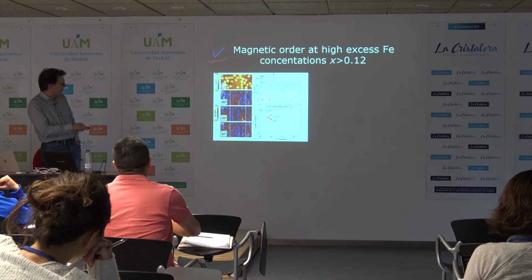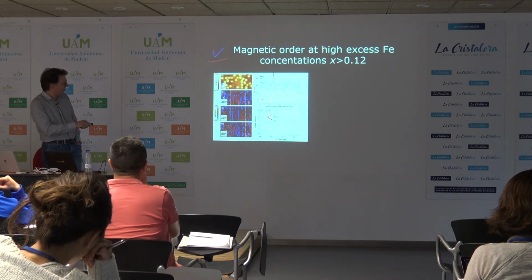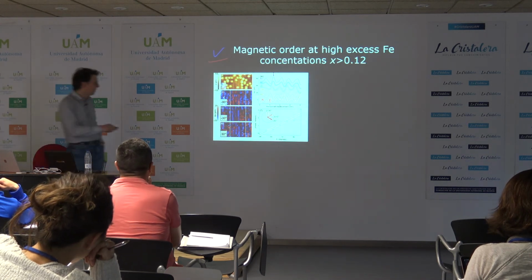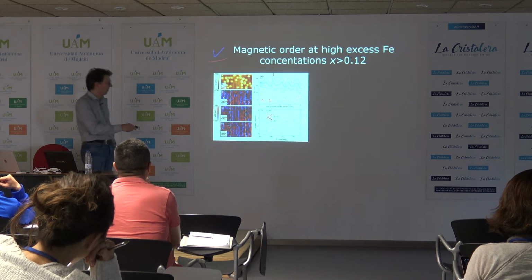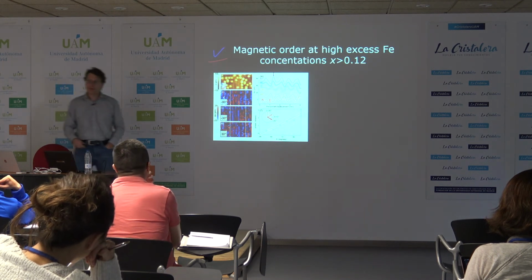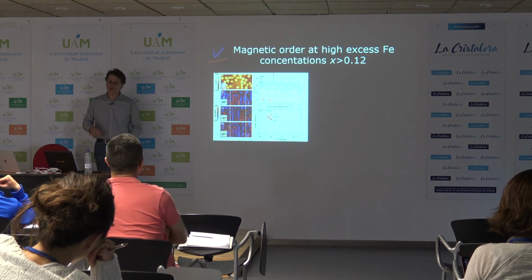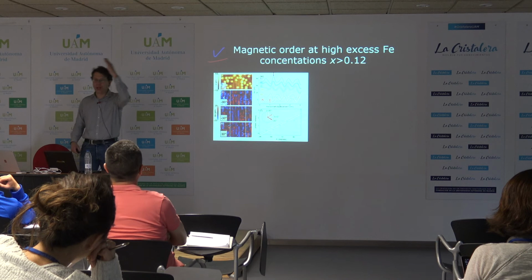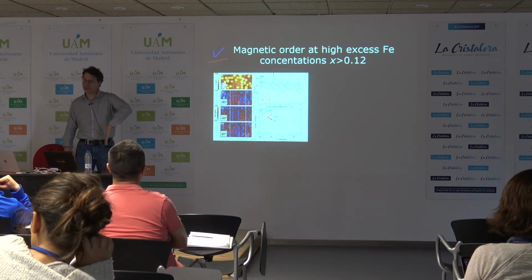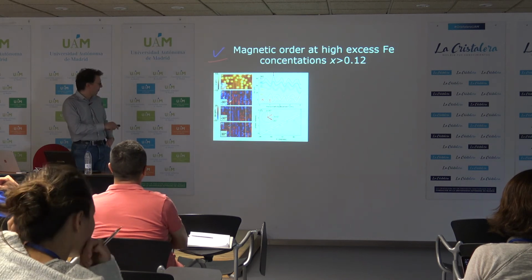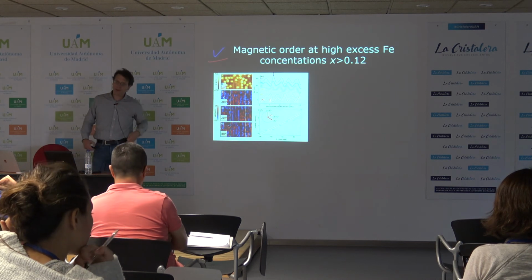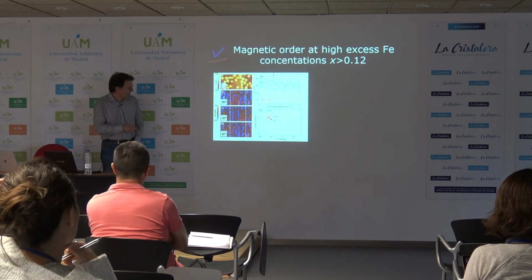It's maybe not so easy to see in these images, but here's a series of line cuts taken in the same location, and you can see that these maxima move as a function of field angle. So we can clearly show that the magnetic order shown here is in fact a spin spiral, and as we project on different spin polarizations of the tip, the phase of the stripe order moves across the sample, which is what you would expect if you image a spin spiral.